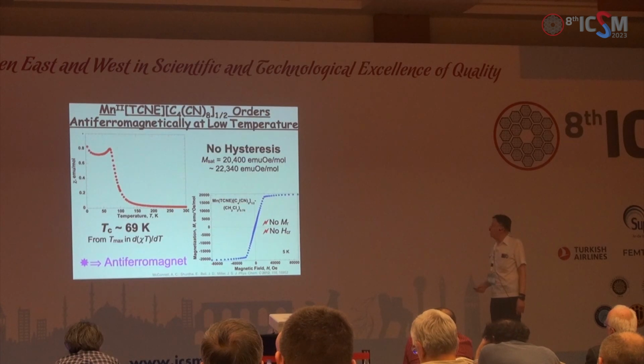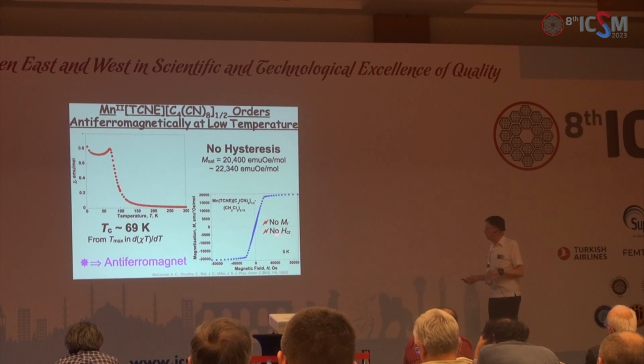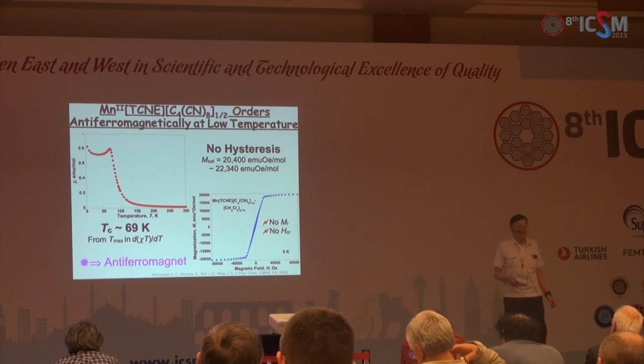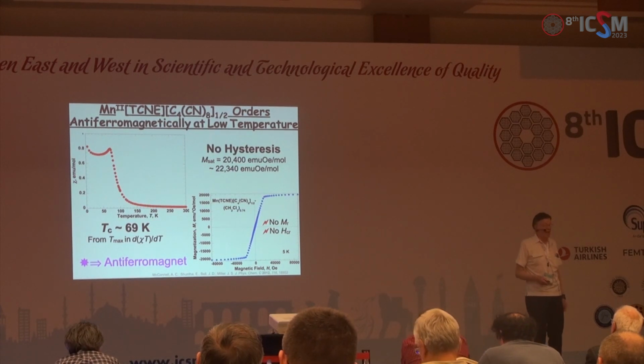Now I'm going to look at the data. I just showed you the chi data a moment ago, and I repeated it here. The cusp here is indicative of anti-ferromagnetic ordering. The hysteresis loop, or lack of hysteresis loop, no remnant magnetization, no coercive field, and other data we have indicate that in fact it is a bulk 3-dimensional anti-ferromagnet.